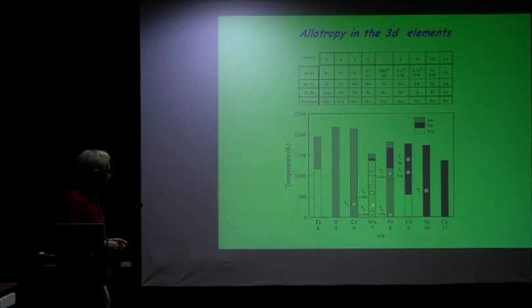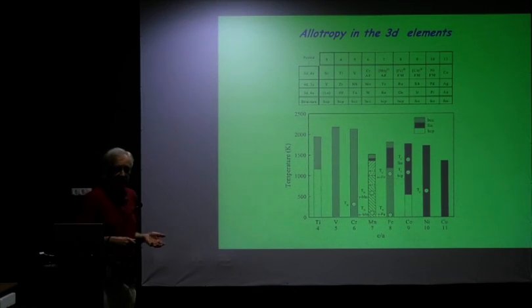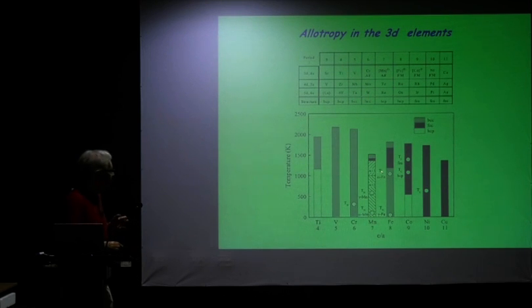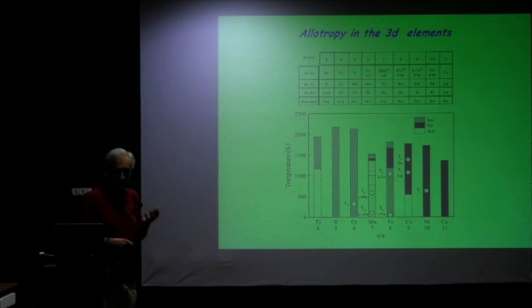You have alpha manganese, which is the so-called A12 structure. It is a complex structure with about 56 atoms per unit cell or something like that. It's a cubic structure though. It's still cubic. And then you have the A13, which is beta manganese. That has 26 or 28, I'm not sure, so many atoms per unit cell. And then when you come to a higher temperature, you have FCC manganese, face-centered cubic manganese.